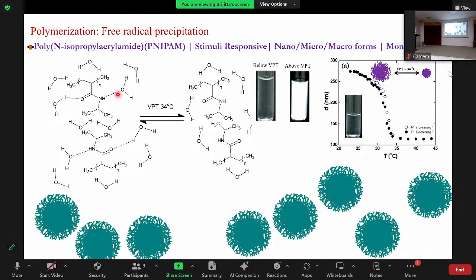I said it is a hydrogel, but it is also called a microgel, which I will tell you later on why it is called a microgel. Being a hydrogel, it is dispersed in water. This means that it can form hydrogen bonds with the water molecules nearby. So when you take a dilute suspension of this colloidal particle and hold it in your hand, because your body temperature is around 37 degrees, in a few seconds you will see that the suspension becomes turbid. This is because when it crosses a temperature of 34 degrees Celsius, the hydrogen bonds break, and the isopropyl groups, which are here, come close by, and then it scatters more of the visible light. So this is a temperature sensitive gel.